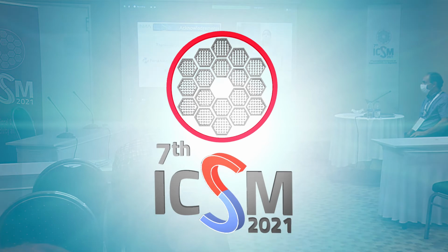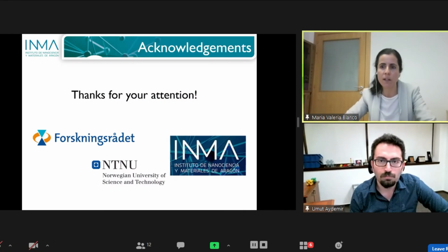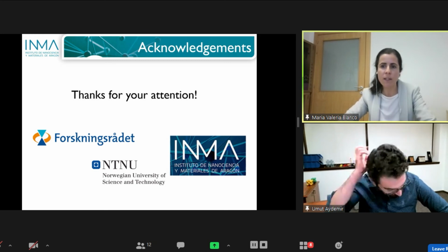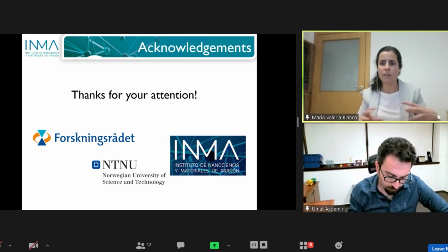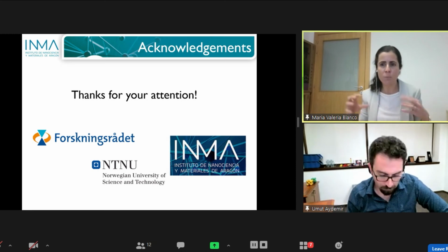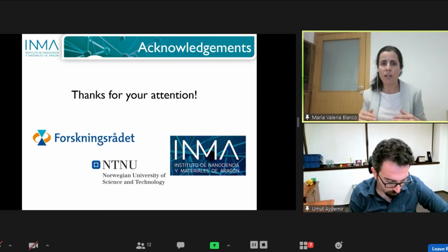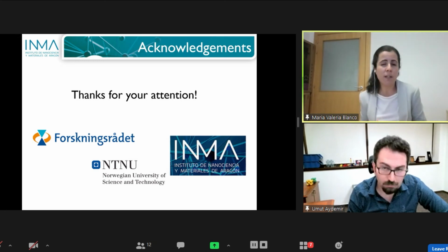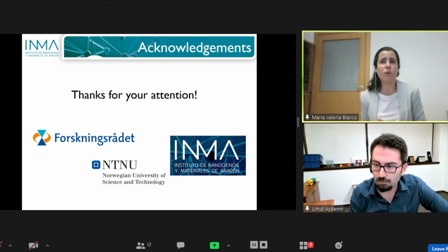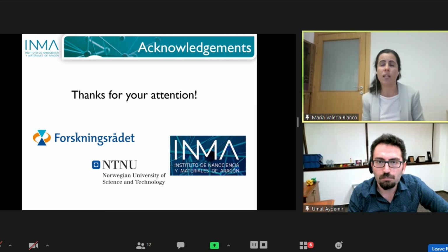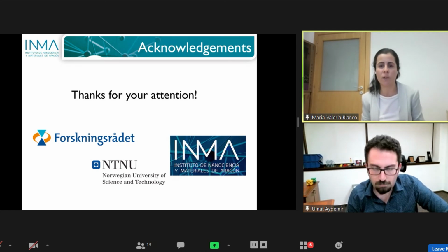No, because I would say that the aim of our work is to be able to cultivate our nanostructured silica. Because later on, if we succeed in this, then you can engineer it a bit: by changing the cultivation media of the algae, you can change the morphology and the nanostructure. So this is the direction we wanted to take. So far, what I know is that with sand, you don't have this internal nanostructure, or even with clay. So we wanted to try with algae because if we make it work, then we can play a lot with the nanostructure.